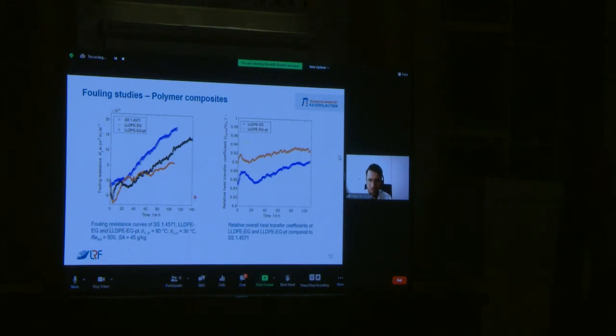And such a drop does not occur for the polymer composites. The results are shown here. On the left, the fouling resistances over time, and on the right as relative heat transfer coefficients compared to stainless steel. So a value of 1 here means that the performance of the polymer composites corresponds to that of stainless steel. And here too, the polymer composites have slight advantages over stainless steel, which is in particular evident here. The performance of the polymers compared to stainless steel increases with increasing test duration.